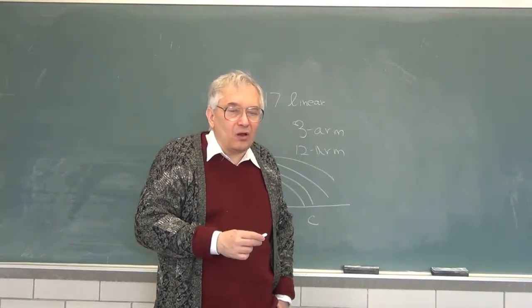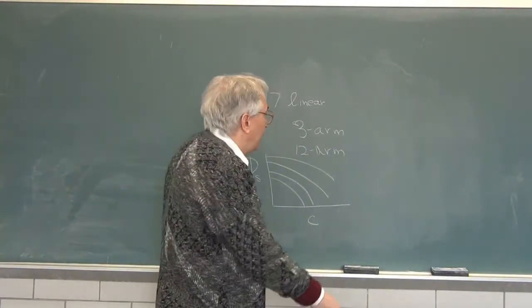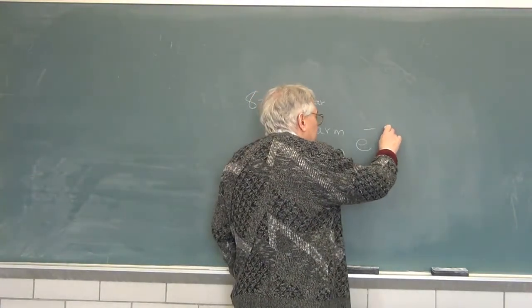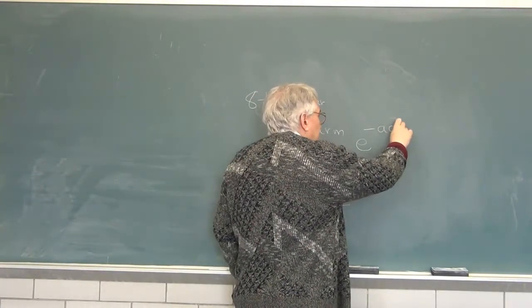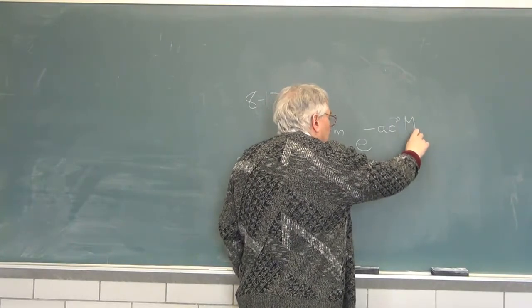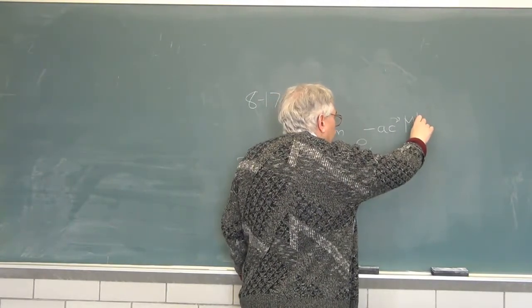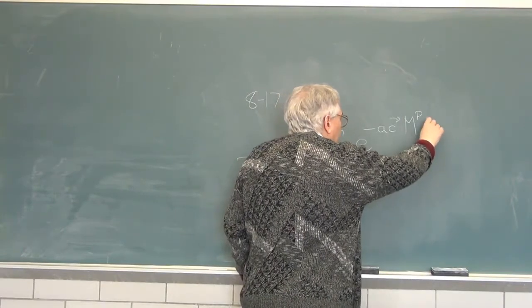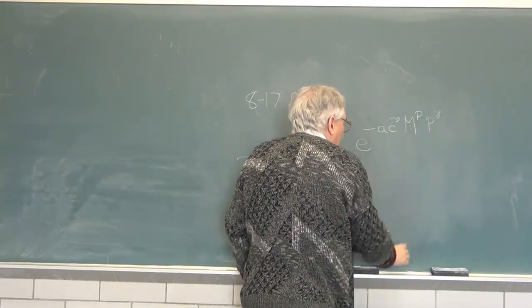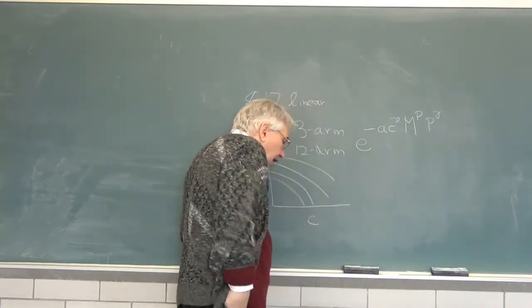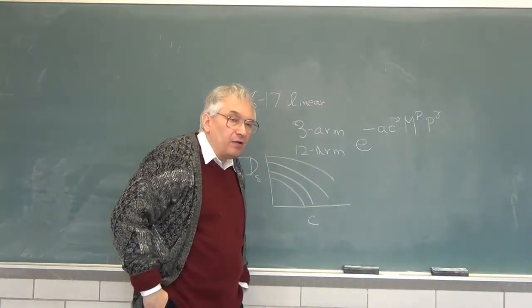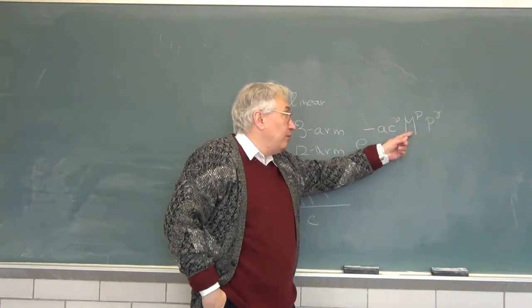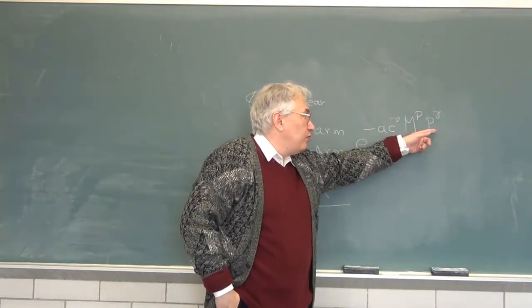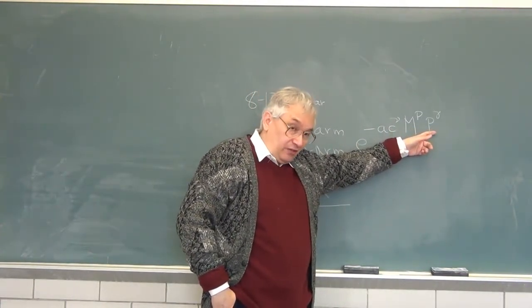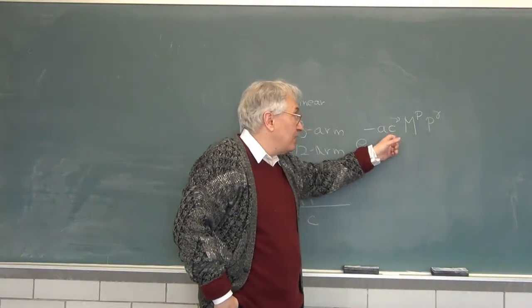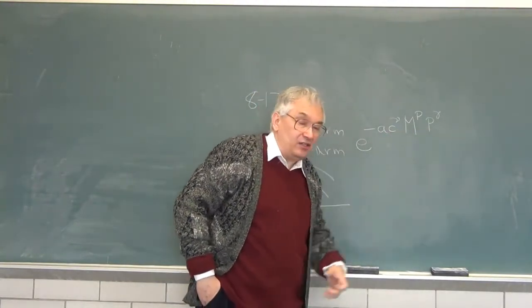And what are those lines? Those lines are stretched exponentials, e to the minus a, c to the nu, matrix molecular weight to a power p, probe molecular weight to a power gamma. And if you work through, there are in fact three different matrix polymers. There are four different probe polymers, yes. And there's concentration. There are 12 lines generated.